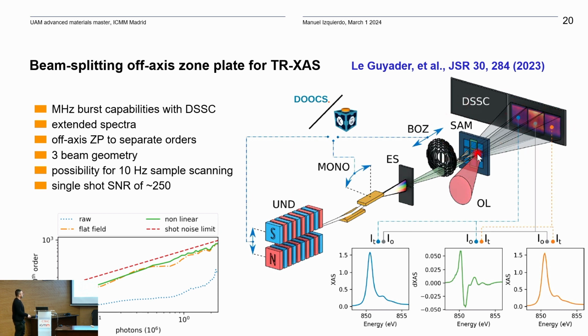So what you normally do is, in these 3 membranes, when you have a thin film, the middle one is empty, so this you will use as an I0. The +1 will be the sample without the laser, and for the -1 the optical laser will be on. From there you can reconstruct the pump minus pump, and all is consistent because you have the information of the 3 signals in the same measurement. This has allowed us to improve the signal to noise ratio by a factor of something like 250, and it is reaching the shot noise limit.